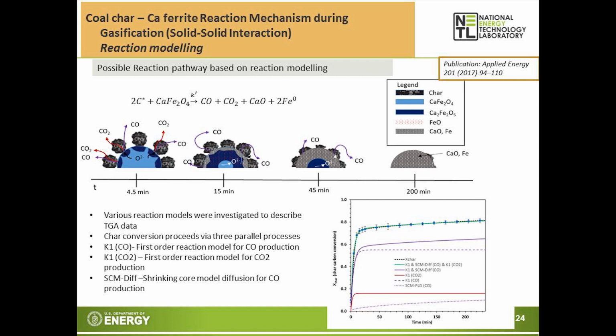So the reaction is shown here. Using the data, we can get this reaction progress. Initially, it's the metal oxide oxygen carrier. The surface reacts with the char to produce carbon monoxide and CO2, and then the oxygen in the bulk transfers through the reduced oxygen carrier layer to react with the coal char to produce carbon monoxide. So later in the reaction, carbon monoxide is the main product.